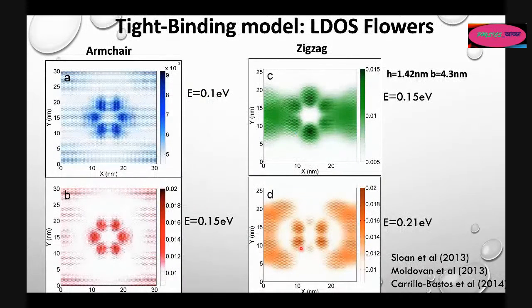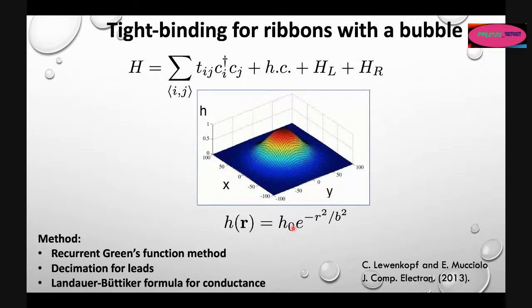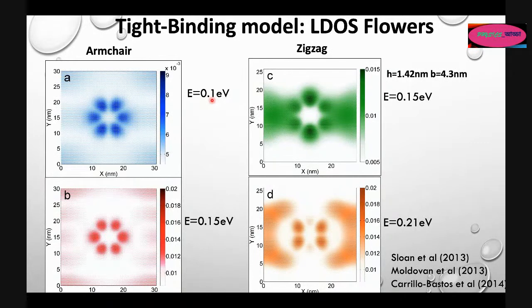Now, with a Gaussian shape, we are able to describe the positions of the nearest neighbors for each atom in our discretized lattice systems. And with these positions, we are able to calculate this Tij, and then we diagonalize the Hamiltonian using standard numerical techniques for this type of problems. And we calculate the density of states, which is nothing else than the charge distribution that happens for this particular system. And what we see is that it doesn't matter in which orientation we put the graphene lattice with respect to this Gaussian bubble. We see that there is an enhancement of the density of states in regions that have the shape of a flower with 6 petals. You see 6 petals with one orientation at different energies, and 6 petals in a different orientation at different energies.